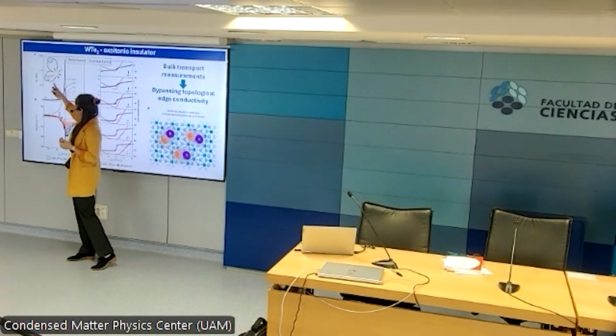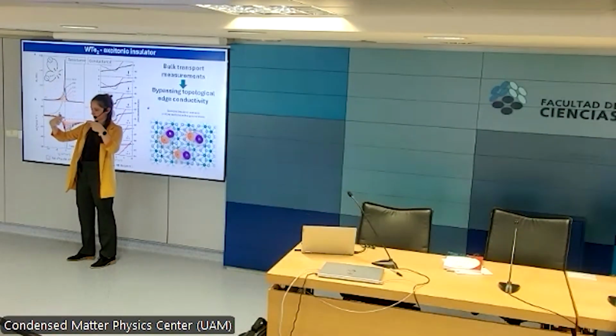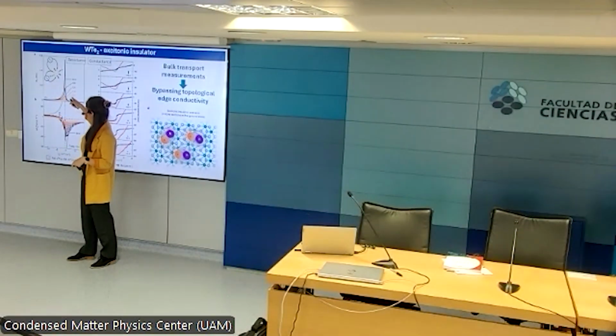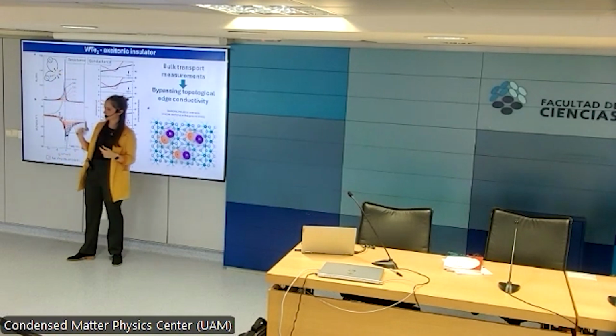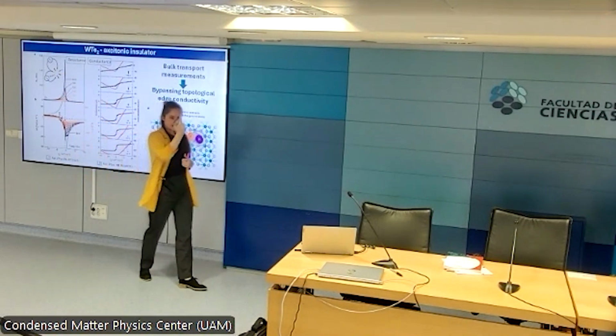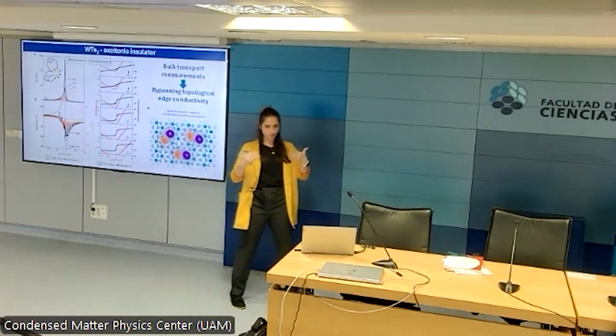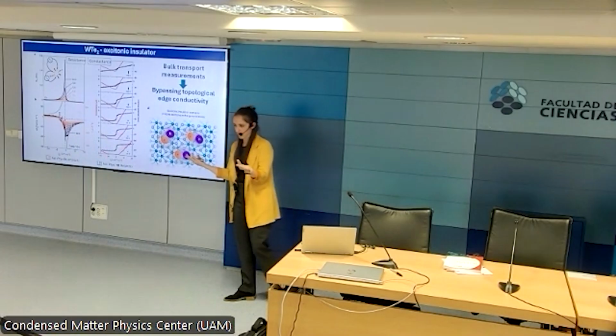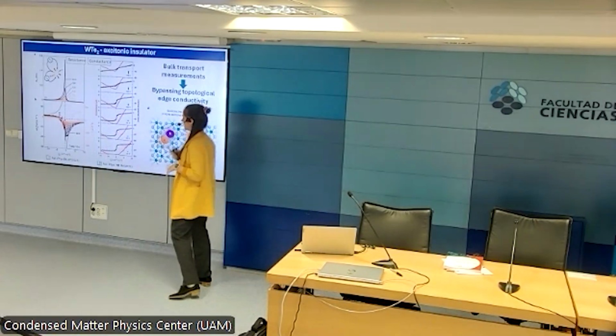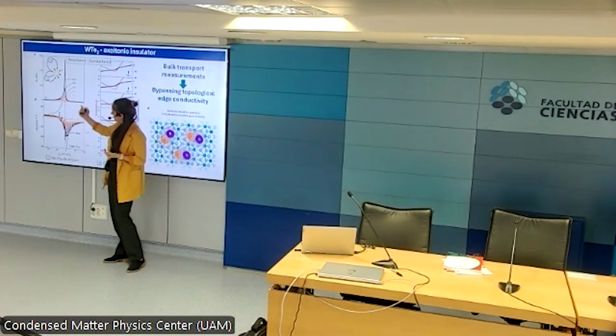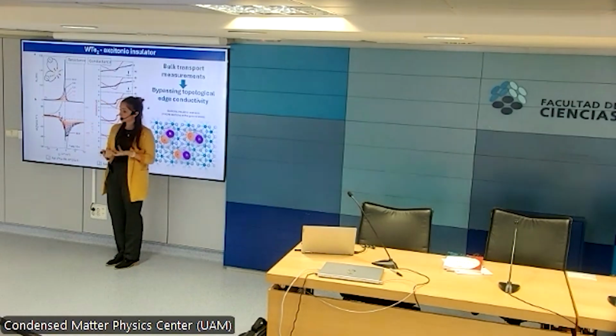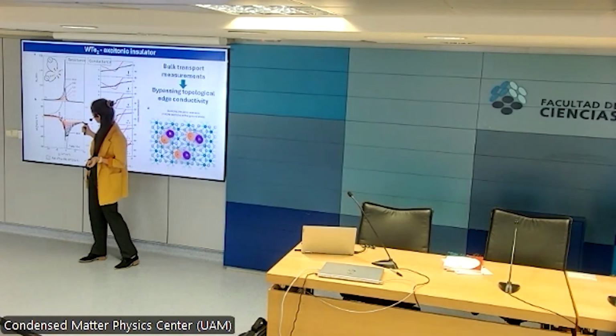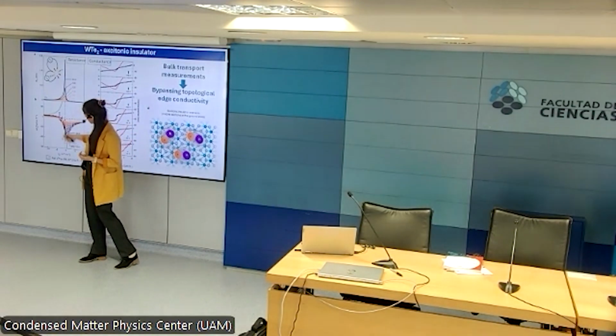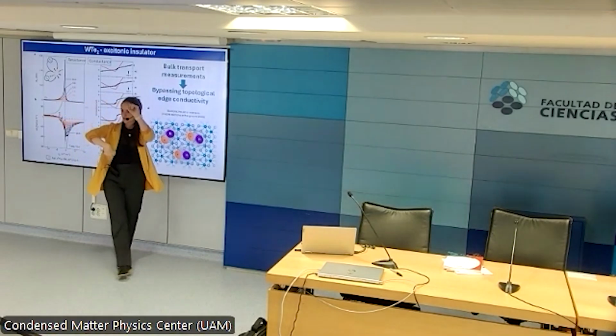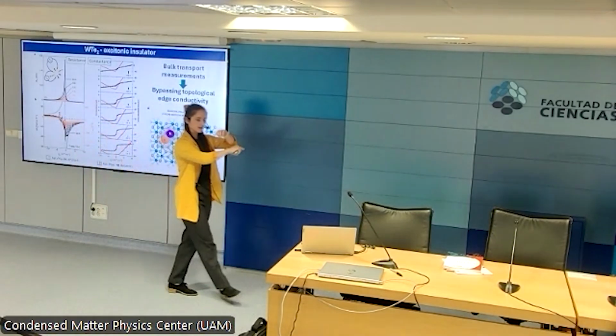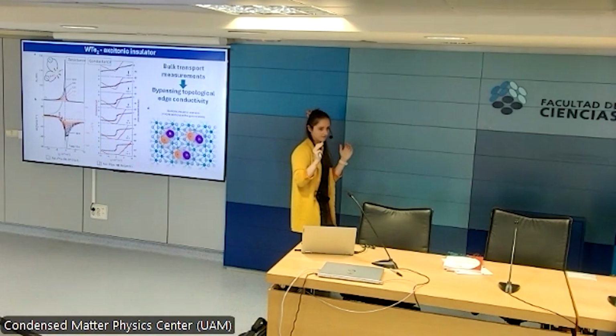They look at normal resistivity measurement, so your RXX, and they can see that as they decrease the temperature, the resistance increases dramatically when approaching zero carriers, which tells you that there's a band gap there. That's nothing funky. What is funky is that if you look at the Hall resistivity, what you would expect for a normal insulator is for the Hall resistivity to diverge at 0 carriers in the opposite direction, and instead of diverging, they see something that is sort of flat at every temperature.